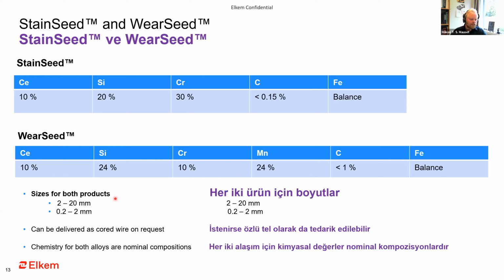The standard sizes that we have for both of these alloys are 2 to 20 millimeter, and then 0.2 to 2 millimeter. But it can also be delivered as cored wire on request. And as I mentioned, the chemistry for both of these alloys mentioned here is the nominal composition.